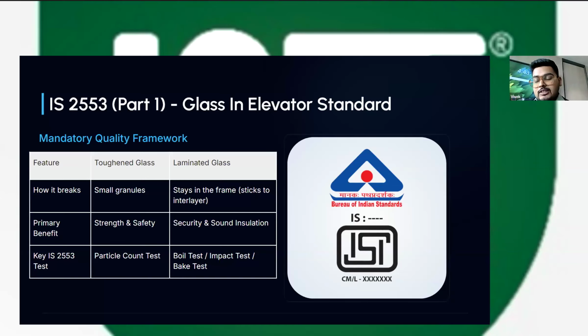Also, the second is the bake test. The bake test uses the same 100 degrees, but rather than putting it into hot water, we use hot air up to 100 degrees Celsius to cover the whole glass and see if there is any bubble formation or any delamination happening. If in either of the two tests the glass delaminates, then it is not a good quality glass. Always know that these two tests are a must, and you should always ask your vendor for a certificate for these tests that have been done on your product.